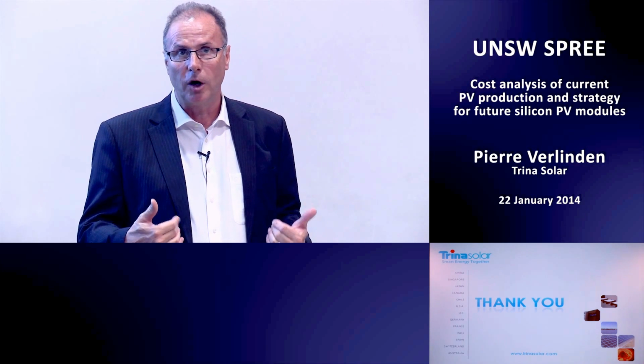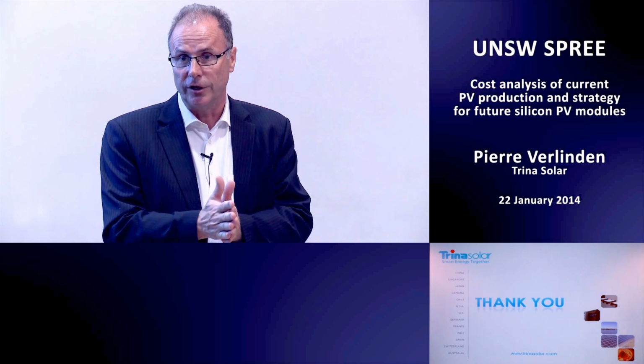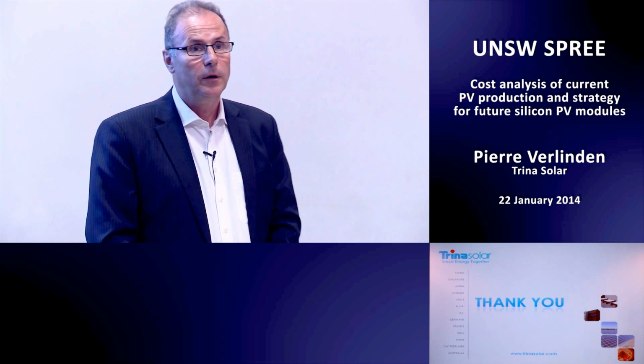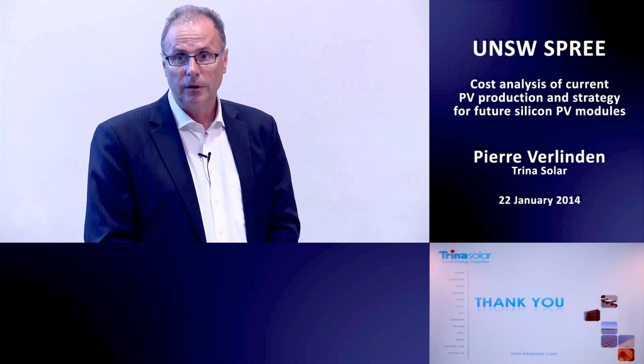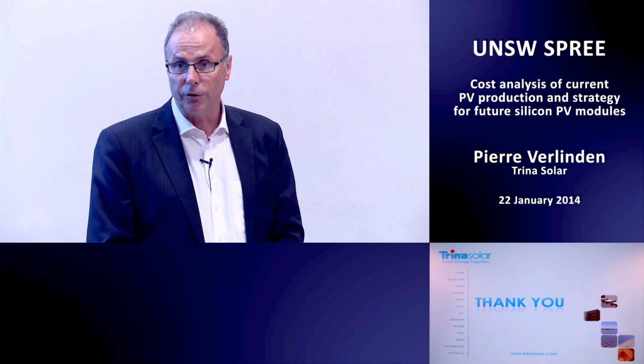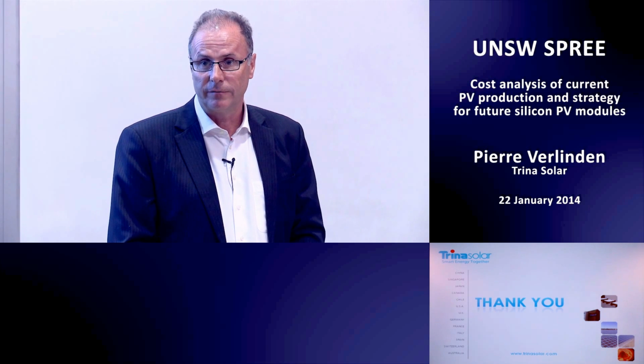Our first modules have about 7 years now of lifetime in the field. So far it's been excellent. Much better than what we guarantee. So we guarantee 0.7% degradation per year maximum, and so far it's been excellent, much better than that.